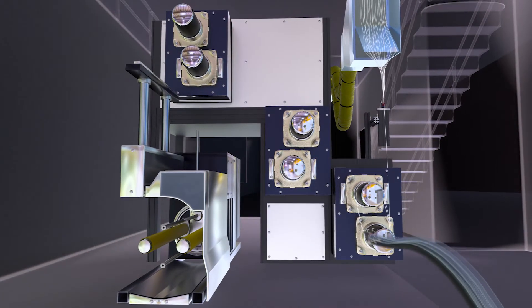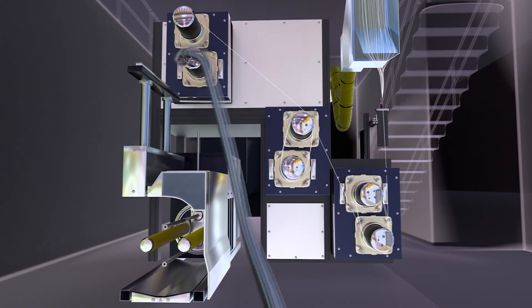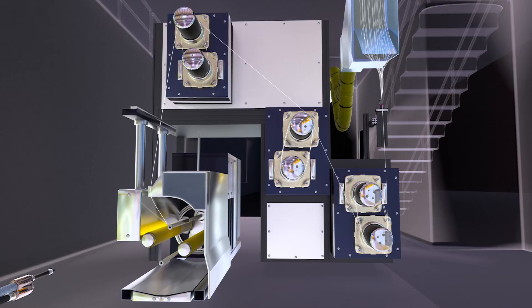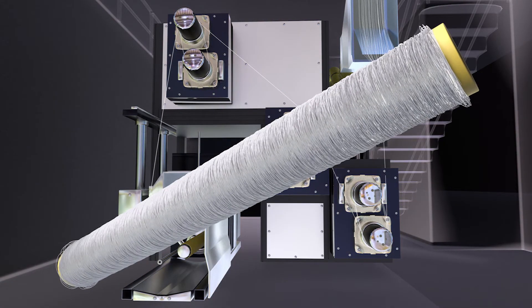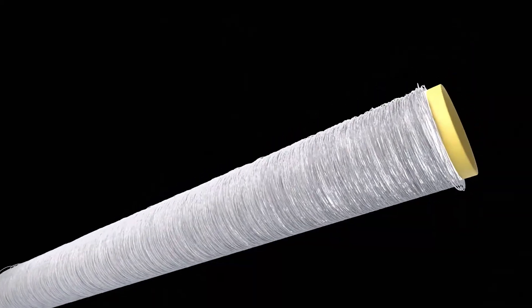Finally, the precursor fibers are wound around various godets and a spinning spool, the final step before packaging. Tow size can range from 3K filaments per strand and up. The solidified filaments are now called continuous fibers and can be widely used in manufacturing.